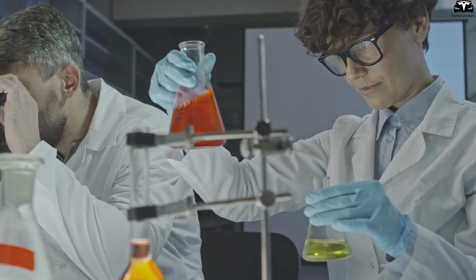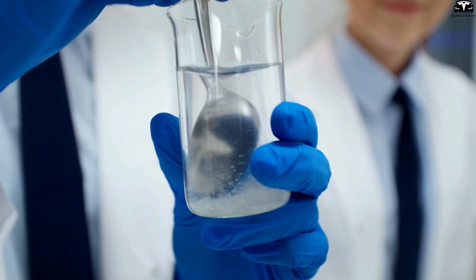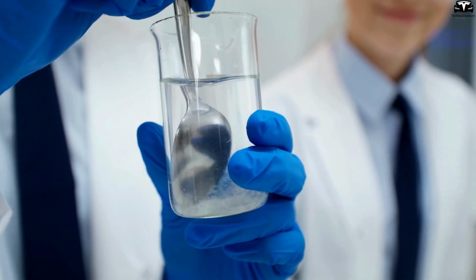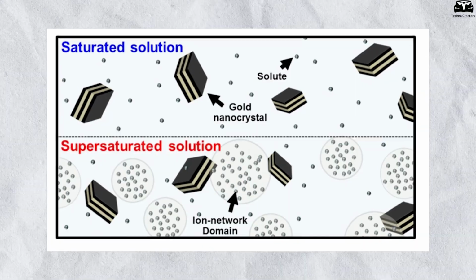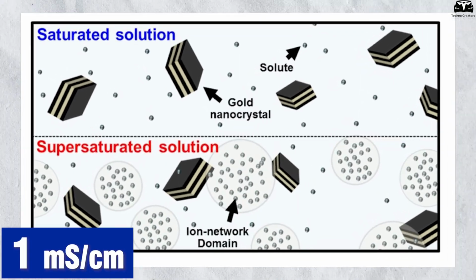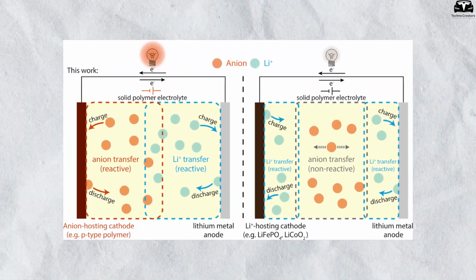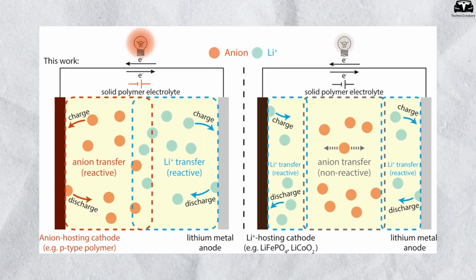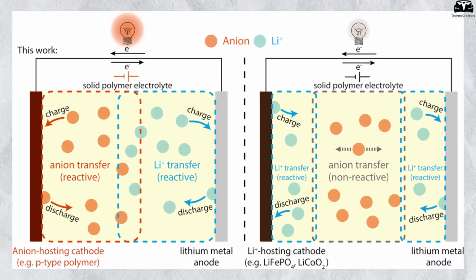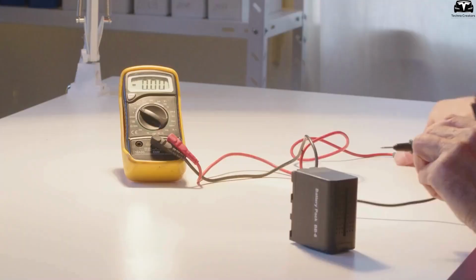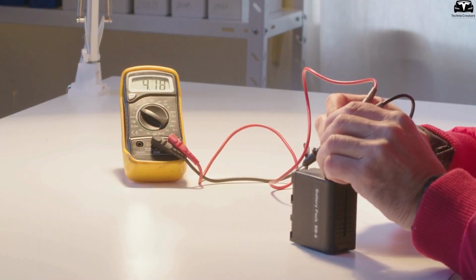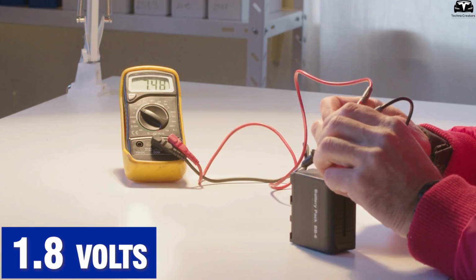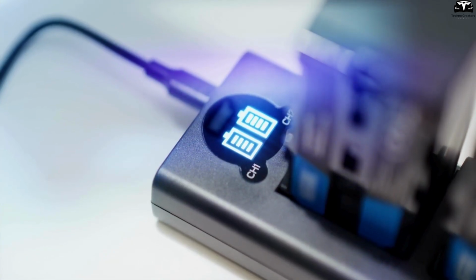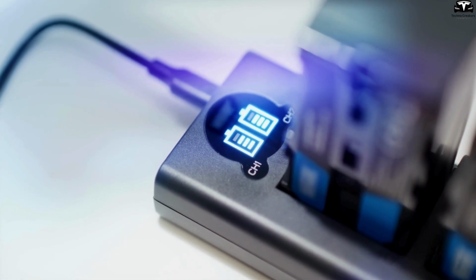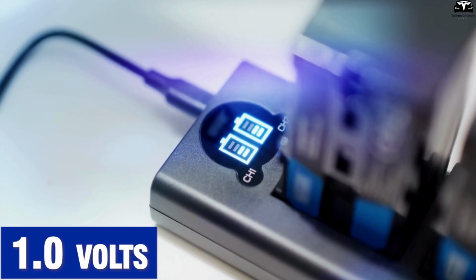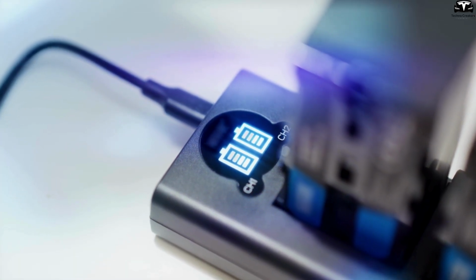Physically and chemically, the polymer network in WiPSE creates a stable environment for sulfonate salt ions with a high ion density, comparable to an ion supersaturation state, boosting ionic conductivity to about 1 millisiemens per centimeter. This porous and tightly bonded structure also prevents free water diffusion, minimizing electrode decomposition reactions that cause energy loss. At the same time, WiPSE maintains a wide electrochemical voltage window of about 1.8 volts, significantly higher than conventional aqueous electrolytes, which only reach about 1.0 to 1.2 volts, providing stable performance and safe operation.